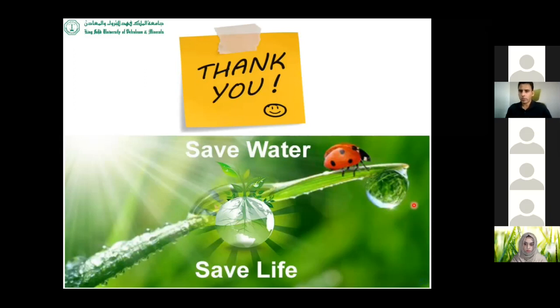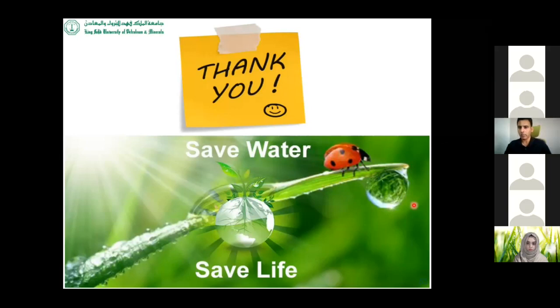Okay. Thank you. This is a nice question. Why we started this work: traditionally, carbon nanotubes were used to improve the characteristics of existing materials, for example, polymeric membranes. People used to add 1% CNT and found that the property of the membrane was enhanced, and when they increased the loading of carbon nanotubes, the properties were further enhanced. We thought that if CNT has such good characteristics, why not use CNT purely? We were trying to use 100% carbon nanotube to fully utilize its properties. But since that was not possible, we keep the maximum percentage of carbon nanotube and a smaller percentage of metal oxide, so that we can fully utilize the properties of the carbon nanotube itself.